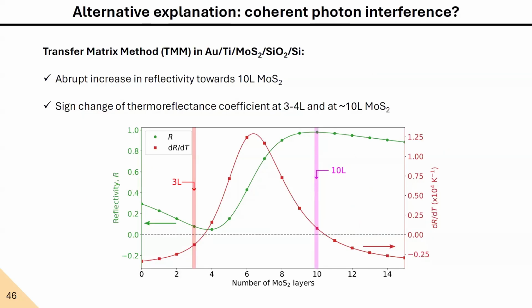Well, as our transducer is so thin, it is possible that we have optical effects playing a role as we change the thickness of our material. And to understand this, we performed transfer matrix method simulations, considering all the materials in our sample with their thicknesses and their optical properties. With this, we can reproduce an increase in reflectivity towards thicker flakes and a sign-changing thermoreflectance signal that crosses zero in between 3 and 4 layers and at around 10 layers, similar to what we observed in our experiments.